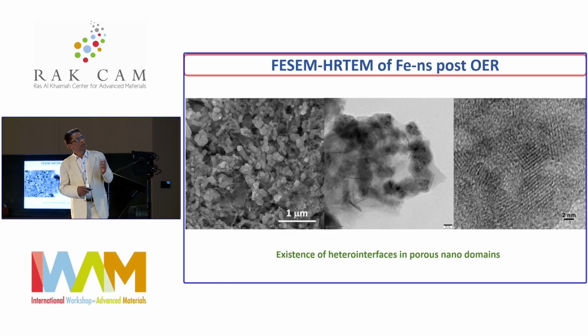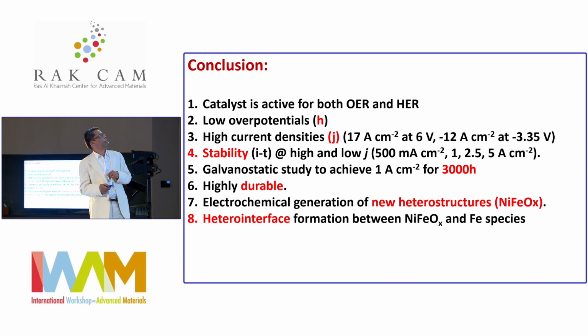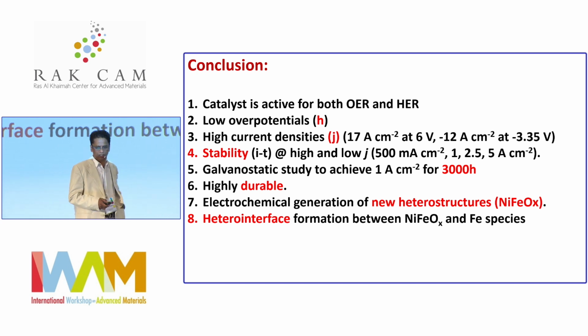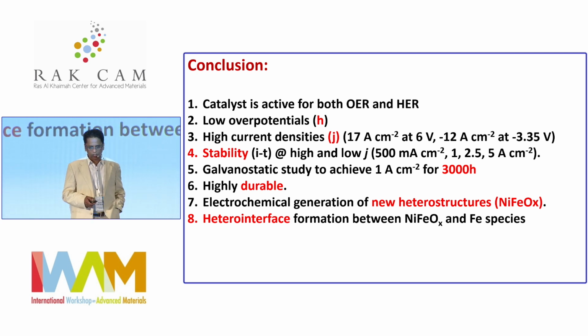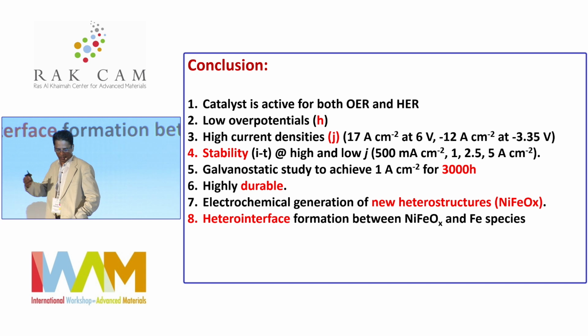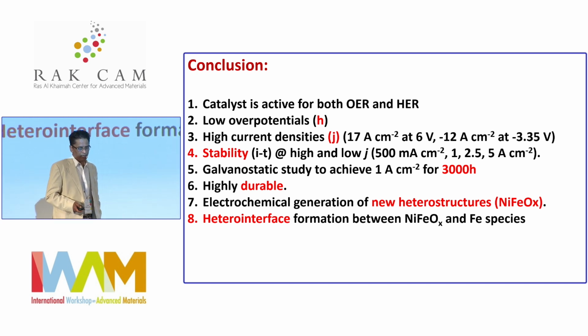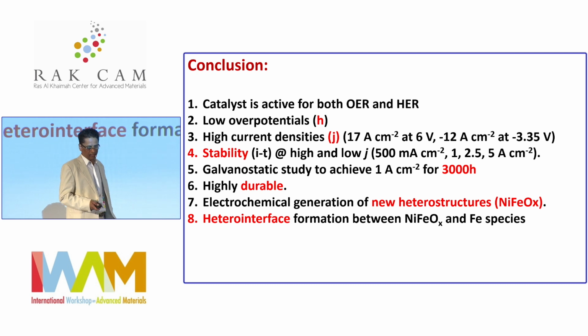So the used catalyst after post reactions shows iron nanostructures with a lot of porous morphology, and it is not clear how the nickel is placed in this kind of system. And to conclude, we have seen that this catalyst is active for both OER and HER, with a very low overpotential, and gives a very high current density. You can achieve up to 17 ampere per centimeter square at higher potential. And even for hydrogen evolution, you will be able to get high current density at a potential of 3.3 volt.